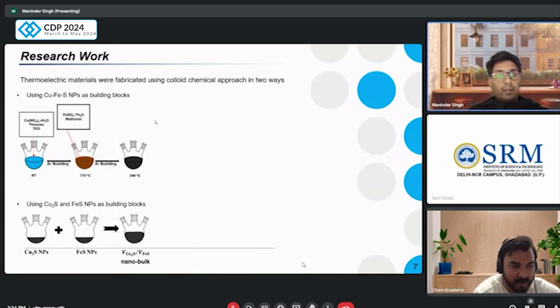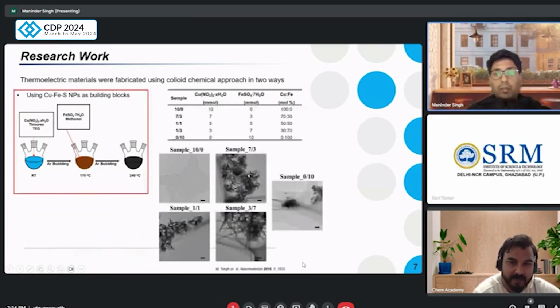So I'll discuss my research work, what I did in my PhD. I created copper and iron sulfide nanoparticles, where I used copper nitrate and iron sulfate precursor salts, and I mixed them together to create copper sulfide and iron sulfide nanoparticles. As you can see, these are the TEM images. I'm not sure whether you're familiar with the TEM instrument, where you can see nano-sized materials. So I created copper iron sulfide nanoparticles in different ratios.